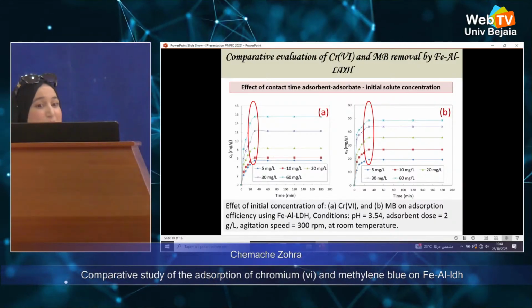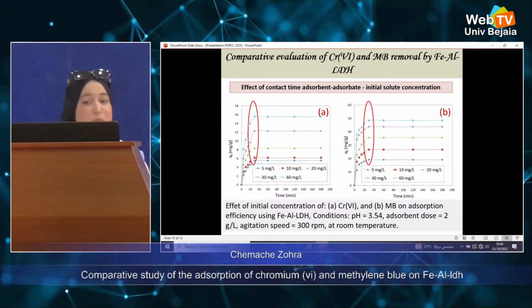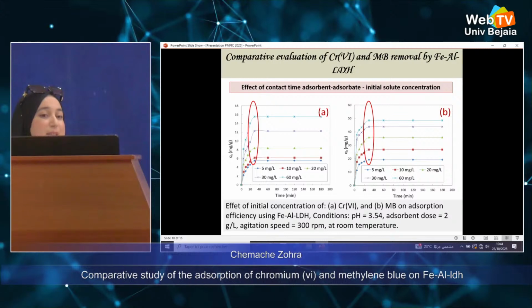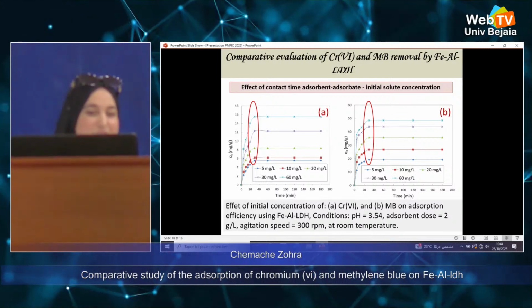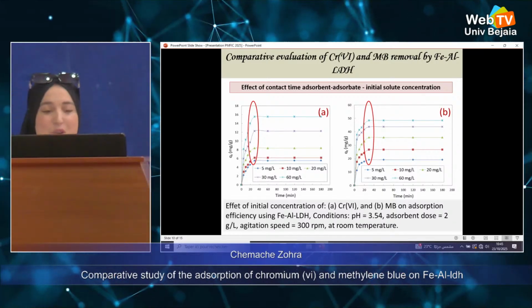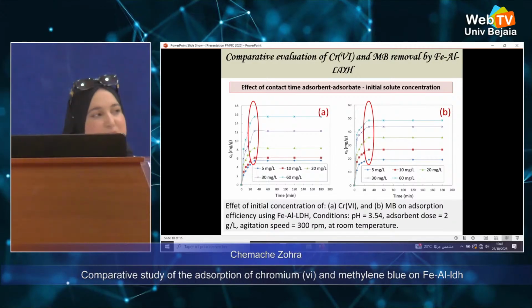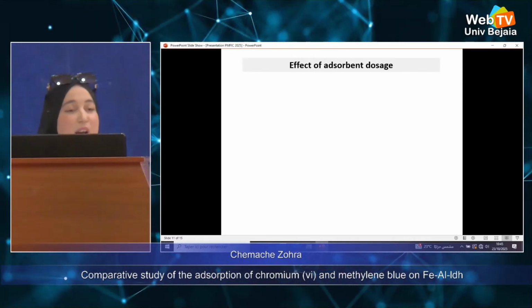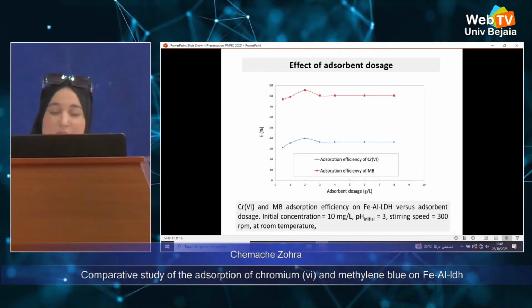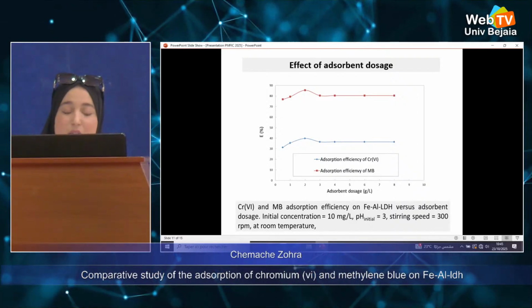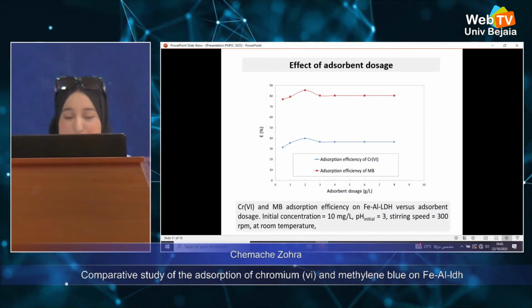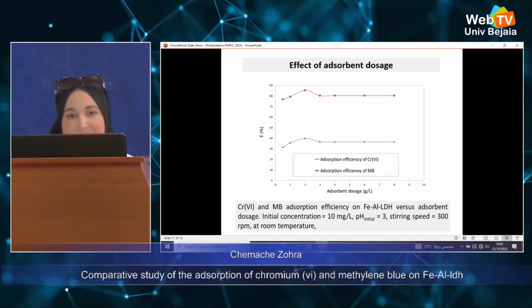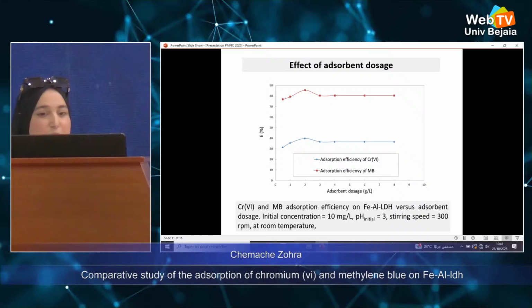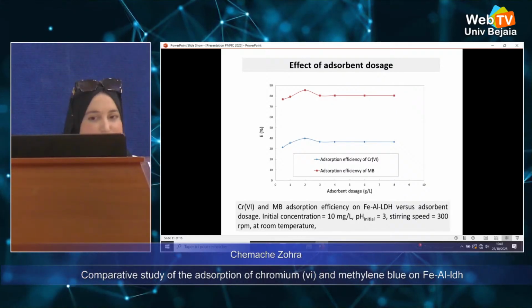We also observed that methylene blue is adsorbed more efficiently than chromium hexavalent due to its cationic nature, which increases its affinity for the adsorbent surface compared to chromium hexavalent. We have also examined the effect of adsorbent dosage. The equilibrium adsorption as a function of adsorbent dosage reveals that 2 grams per liter provides the optimal adsorbent dosage for the two systems studied.